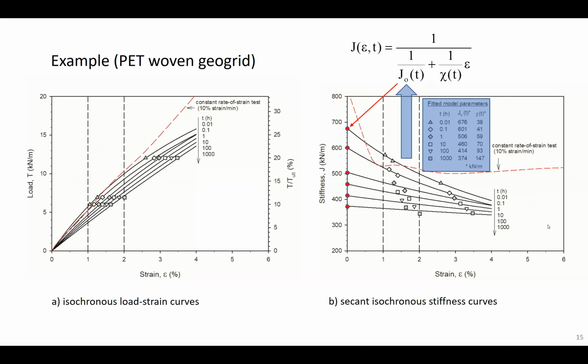This slide shows another material. This is a PET woven geogrid. And again, you can see on the left-hand side the isochronous load strain curves at different hours. You can see the constant rate of strain test, again, falling well above those curves. And then from this data, this 2-parameter isochronous stiffness equation has been fitted.